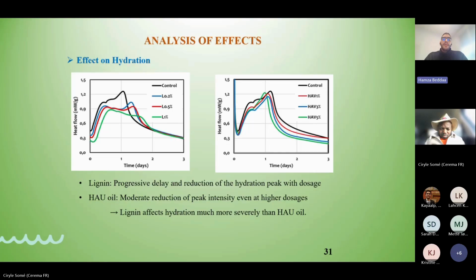On the other hand, using the waste vegetable oil didn't show any delay, but we can see just a decrease in the intensity of the peak. It's due to limiting the contact between water and cement, due to introducing more air and the hydrophobic nature of oil.